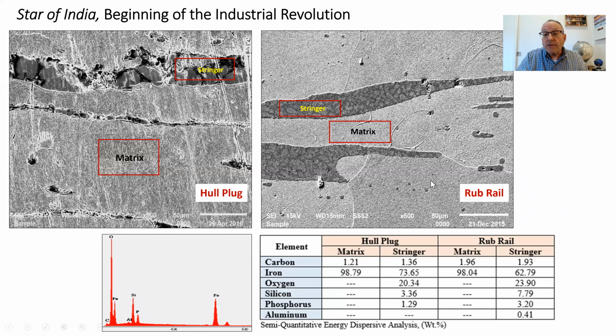And so this is the hull sample and this is the rub rail sample. And we did a sample of the matrix and the stringer in both of those. And what we see here is if you look at the matrix, sure enough, it's a low carbon steel in both those samples. If you look at the stringers, you see, yeah, carbon and iron, but we also see a lot of oxygen, which makes sense because they're non-metallic oxides. So oxygen combined with things like silicon and phosphorus to form these stringers or inclusions. But the interesting thing is, look at the high phosphorus content that we see in here. And that was kind of unusual. It was a good marker for the different types of processes that we wanted to explore.